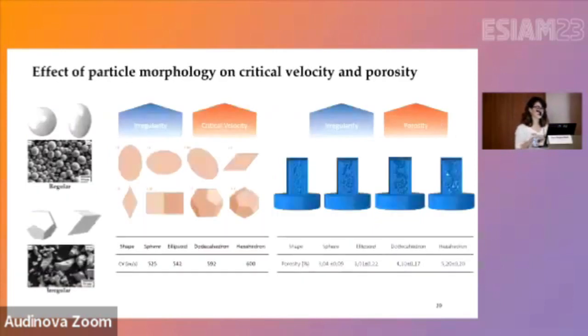And once it's validated, we have used it to estimate different quality indexes. In this case, you can see, for example, the effect of particle morphology. We consider two typical, very ordered and regular geometries, and then representative shapes for irregular geometries, considering all possible rotation angles of impact for each of these shapes, and see how they would affect the critical velocity, or the overall porosity that we get when we have multiple particle impacts.